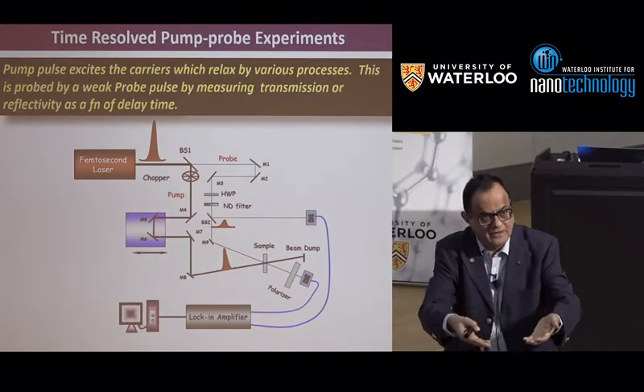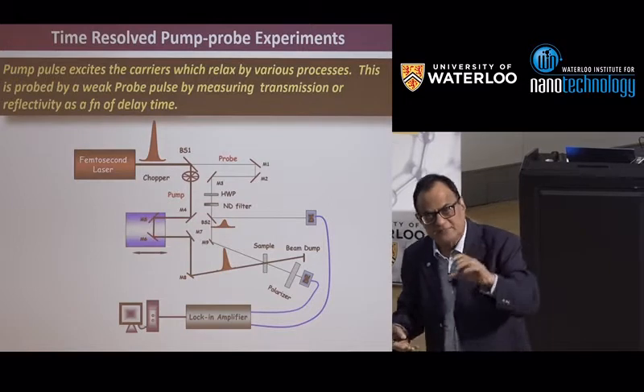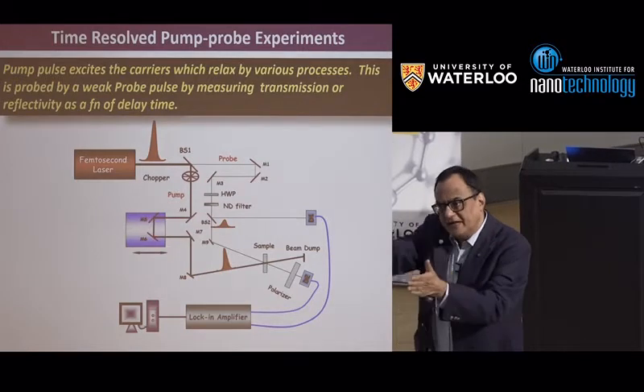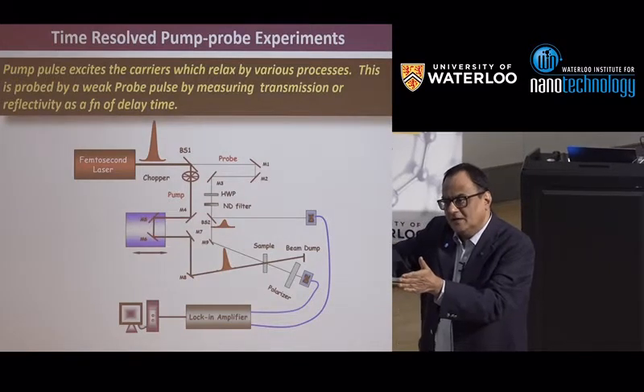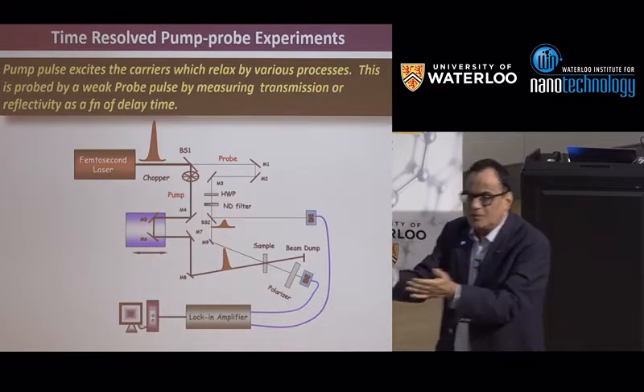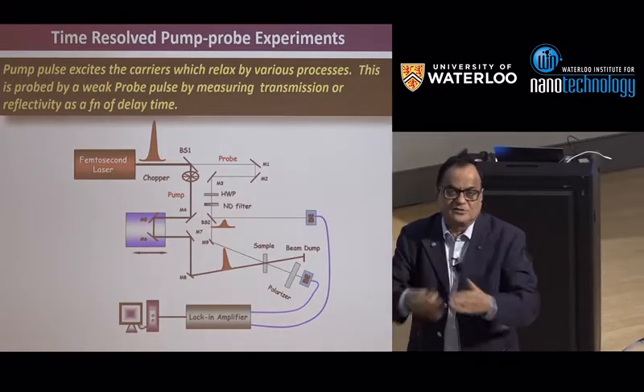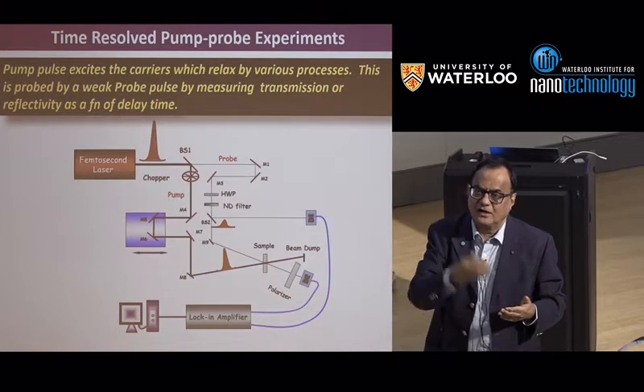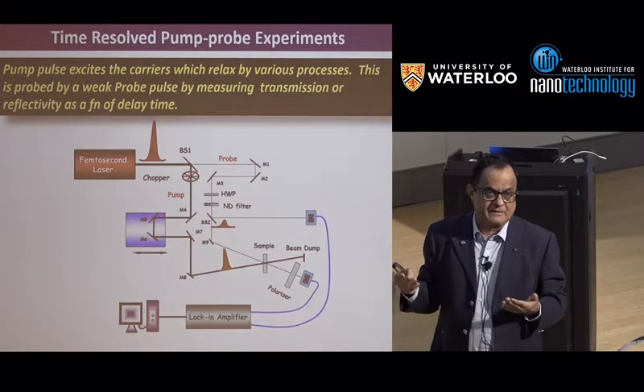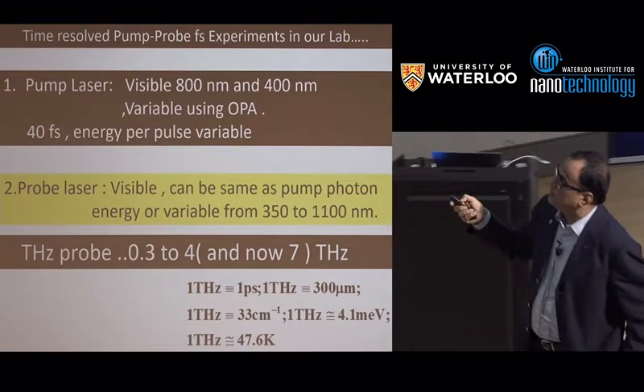You need to read out. So you send a probe pulse, which is a very weak pulse, at different delay times, and ask what is happening to the probe pulse, how much it is reflected or transmitted. So that information is quantified in these experiments. Now you have many possibilities.